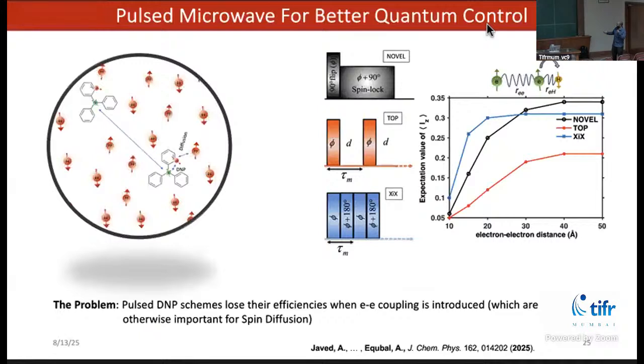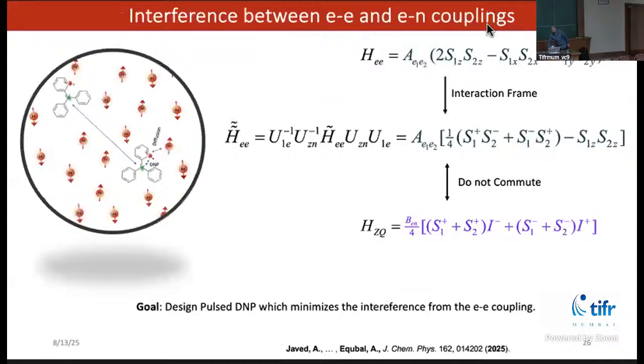What I am showing here is the efficiency of these techniques as a function of electron-electron coupling. When the coupling is weak, they are efficient, but as you increase the coupling by shortening the distance between two electrons, they become more and more inefficient. So all the pulsed DNP techniques which were developed until very recently don't tolerate the electron-electron coupling. What we have recently worked on is to overcome this limitation. The reason electron-electron coupling interferes is that the Hamiltonian for electron-electron coupling does not commute with the Hamiltonian for electron-nuclear coupling. If two things don't commute, they interfere with each other.